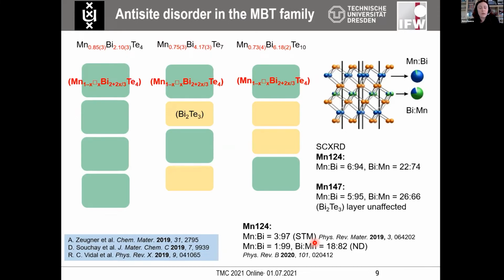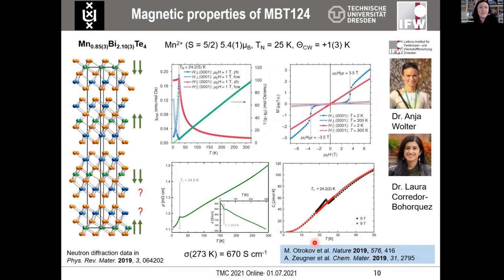So this disorder was considered a little bit as an annoying factor, but not something that actually drives the properties of the material. One can see it also in the consistency of the magnetic properties of 1-2-4 phase that was reported to be a three-dimensional antiferromagnetic compound. So you have here out of plane ferromagnetic coupling between the manganese 2+ sites in each septuple layer, and then they order antiferromagnetically in the interlayer direction. So this data, as I said, was obtained also by many other groups, and the role of these additional interstitials, manganese in the bismuth position, was back then not that obvious.